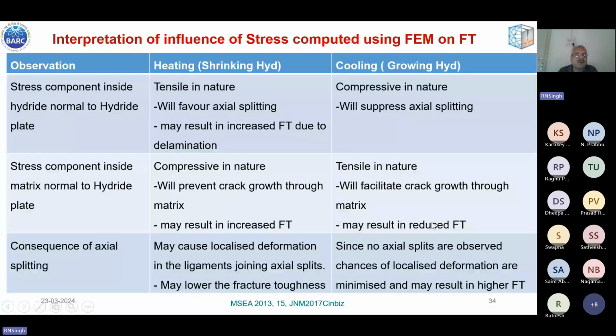And consequence of axial splitting is that it will cause localized deformation in ligaments joining axial splits. It may lower the fracture toughness. Whereas since no axial split is observed in case of cooling case, chances of localized deformation are minimized and may result in higher fracture toughness. So ultimately, axial splitting and localized deformation is affecting the fracture toughness. So that's why in case of heating case, we are ending with lower fracture toughness.